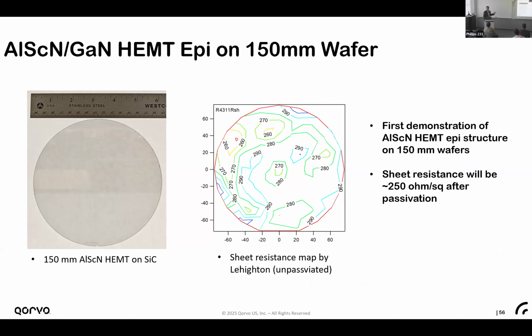At least at Qorvo, by MOCVD we use MBE to grow the ScAlN, and we have achieved a pretty uniform sheet resistance. After passivation, we expect the sheet resistance to go to 250.